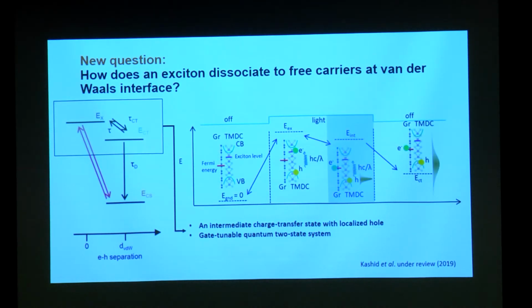So this is the final. This is the present situation. We now have found, I believe, that there is an additional state which is a charge transfer state, when the electron is in graphene and the hole is in the chalcogen layer, where the whole wave function is a localized wave function, which is a high energy state here. And it's exciting for us because this intermediate state can actually be tuned with energy, leading to a gate tunable quantum two-state system. One could probably use it for a different purpose altogether, but understanding this intermediate state was particularly essential in a hybrid of this sort.